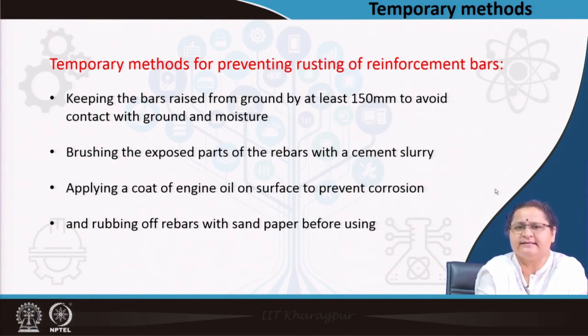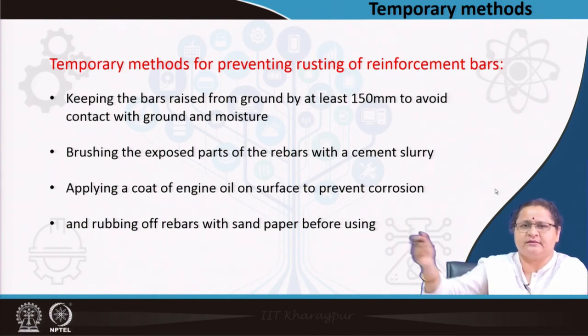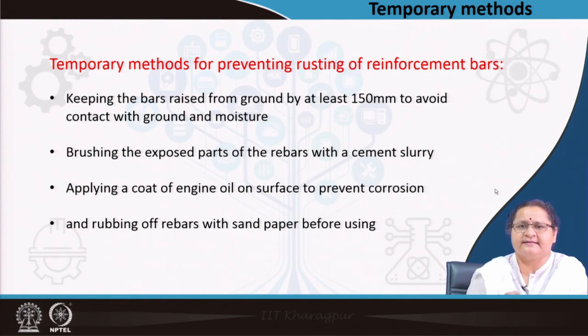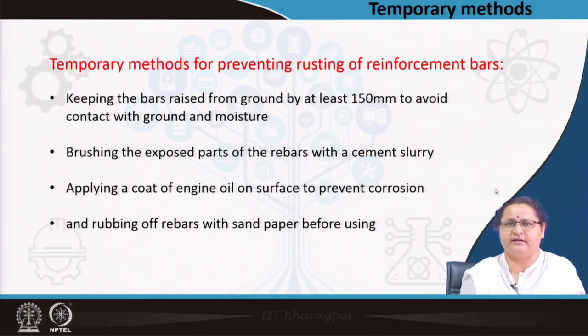You can just put bricks as a support below at an interval and raise the entire steel bars and keep them free from the ground, so that the water does not come in contact. Then you brush the exposed parts, whatever you can see, with a cement slurry. Why cement slurry? Because later on it will be embedded in concrete, where cement will be one of the components. So, it does not need to be taken out, and you are only putting it on the exposed part. You are not opening and individually painting it with cement slurry.